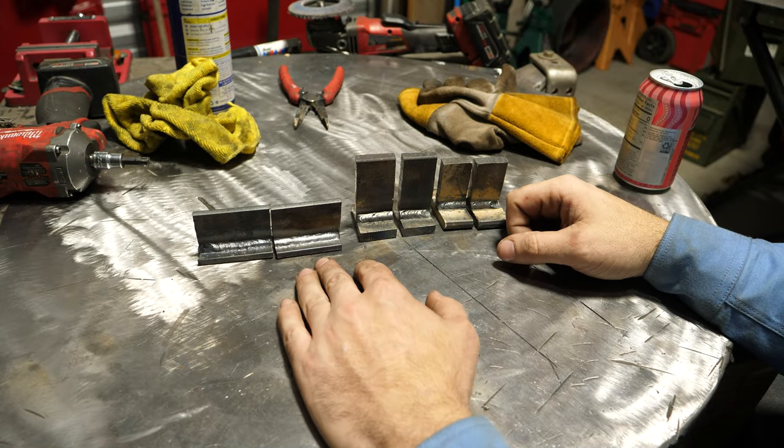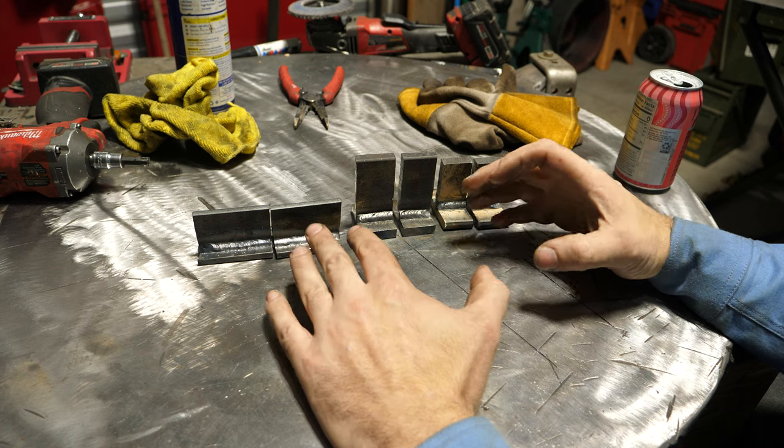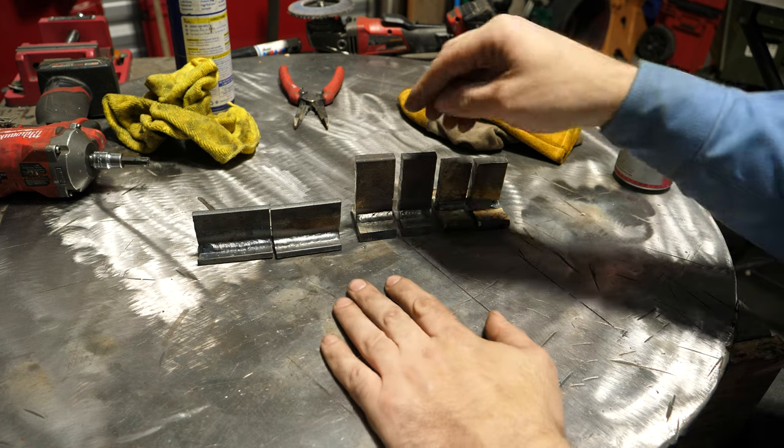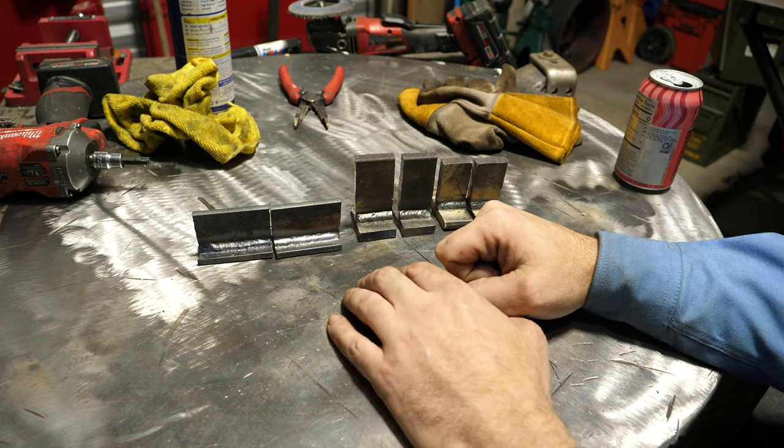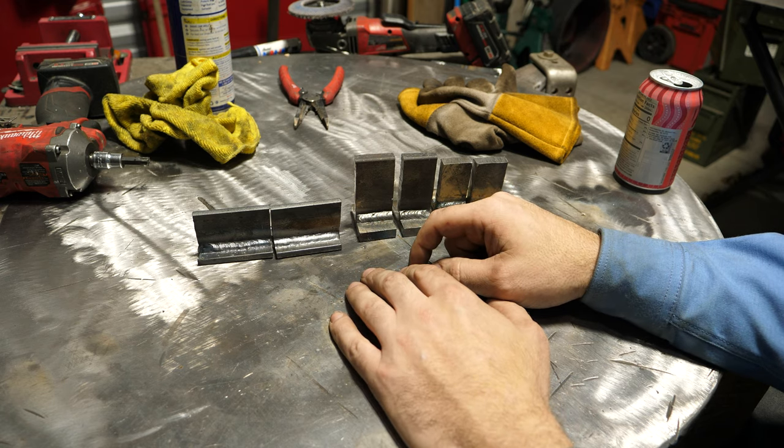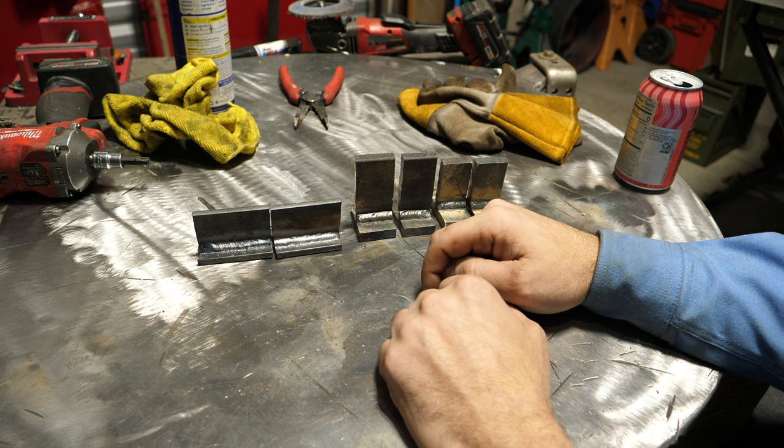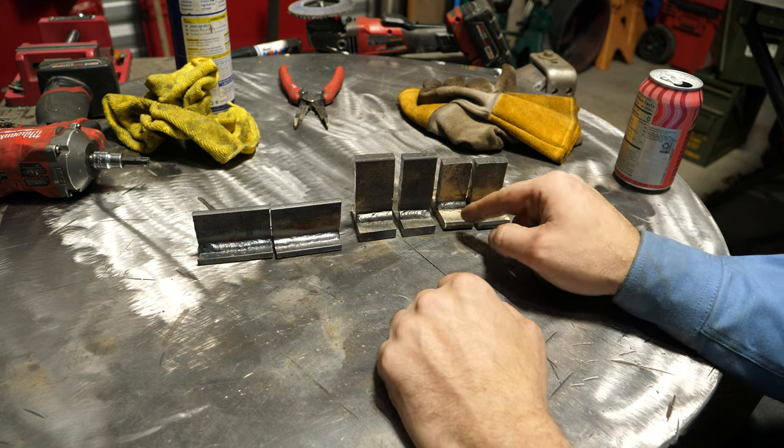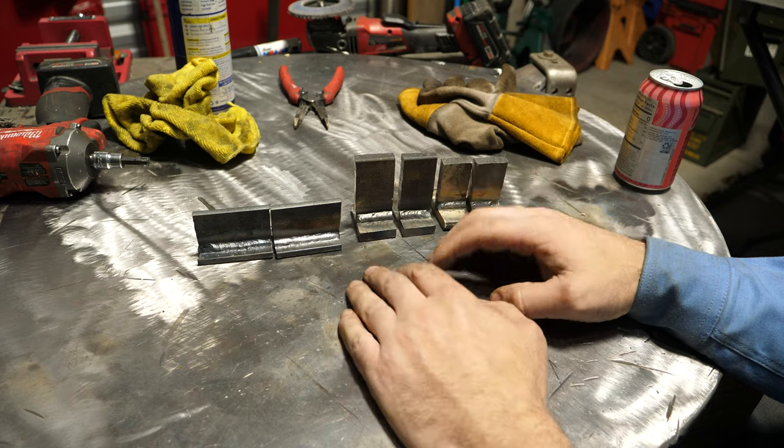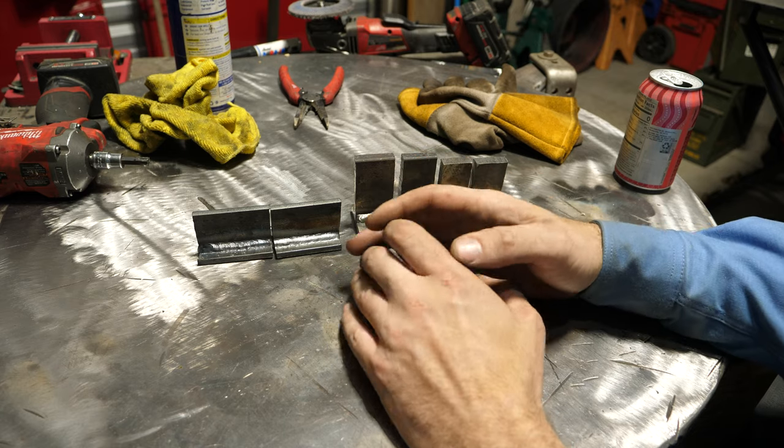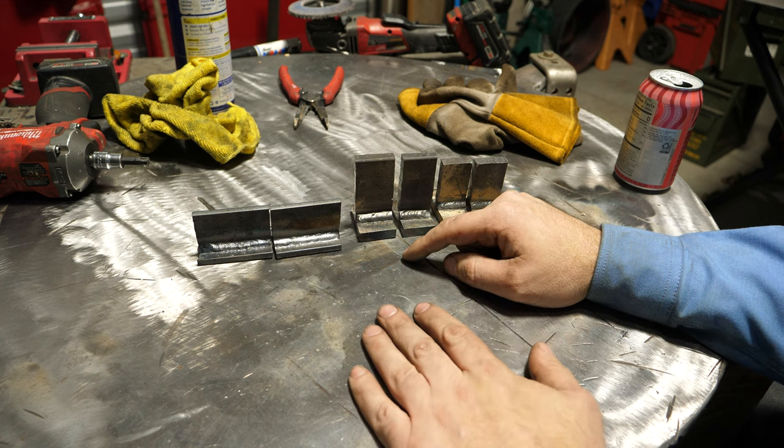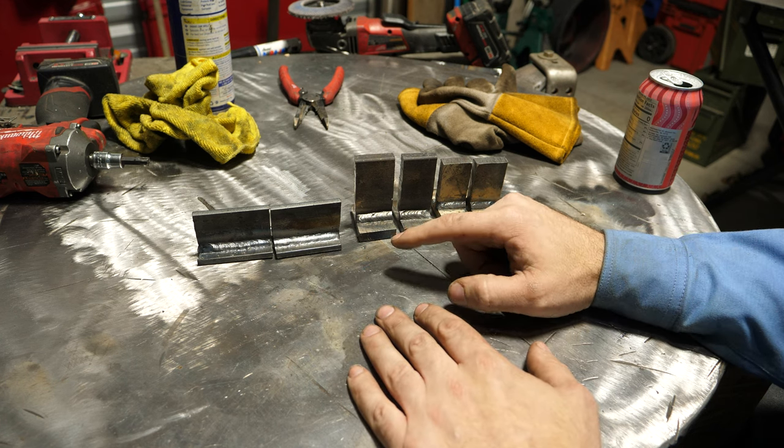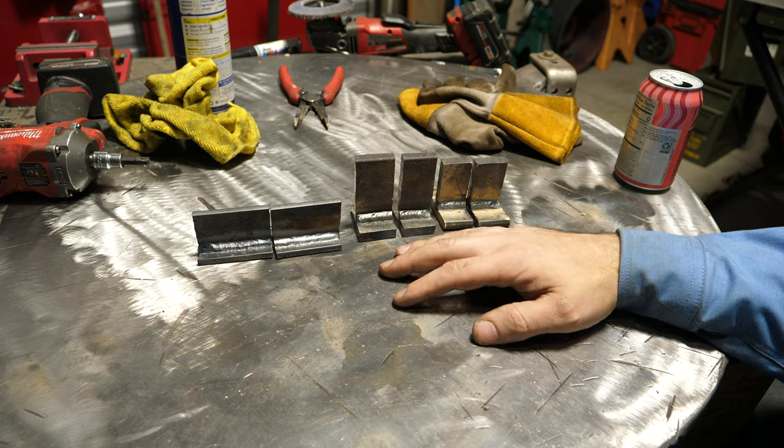Pretty interesting results. In some respects it's what I expected. These plates where I did a circle movement, which I probably shouldn't have done, well guess what? I lost penetration because of it and then gained it back by just going straight in with slightly hotter settings, ever so slightly. But it goes to show that minor differences can make a huge difference in the weld performance.